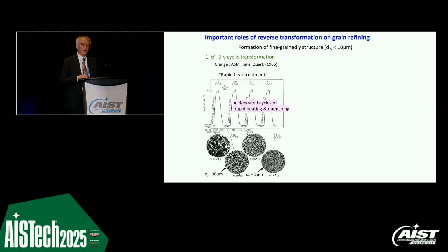So in the case of ultrafine grain, of course, in the 60s we know the rapid heating and quenching technique proposed by Grange produced ultrafine grains of the austenite. So as a result, by quenching, we can get the ultrafine-grained martensite steel. This is one case to get an austenite grain size of less than 10 micron.